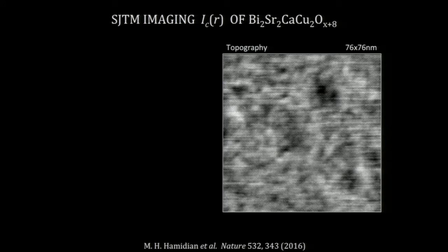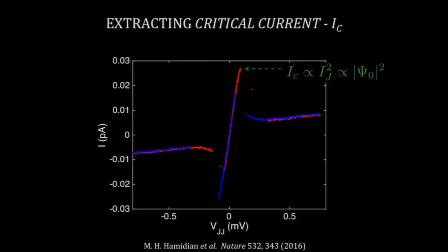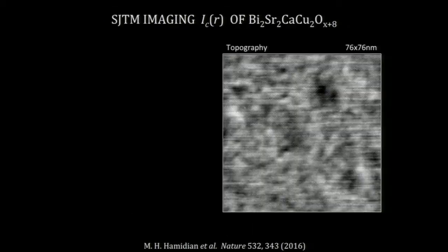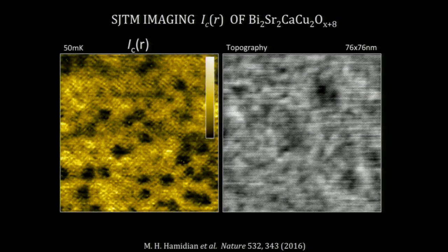Okay, so here in regular tunneling mode, we pull the tip back, take a topographic image, and in that same field of view, you want to measure these curves at every spatial location and extract that peak height. And that'll give you I sub J squared as a function of position. And when you do that, that's what you get. Well, you said, okay, is this really a measure of the superfluid density or the order parameter in the system? And the way to find that out is, well, you want an on and off switch. If you could turn the superfluid on and off and then see how that image responds, then that would be a good answer. Well, luckily nature was kind to us and it gave us zinc atoms.